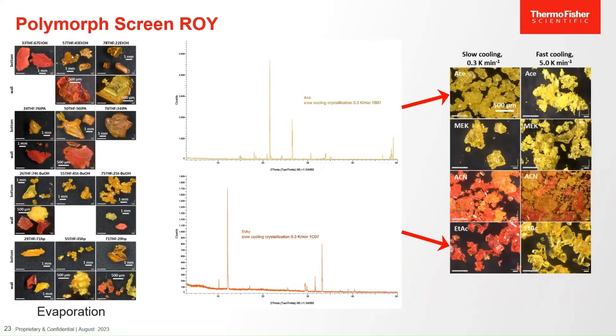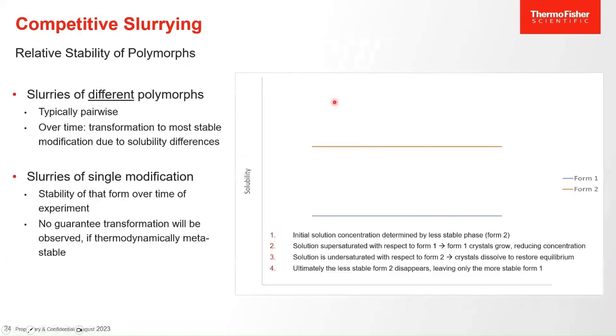So here you see an example of outcomes from a typical polymorph screen. This is a sample compound that we've used for demonstration processes. The compound is commonly known as ROY, red, orange, and yellow, and it's pretty obvious why it carries that name. Different polymorphs have different colors. They can be identified in some cases simply by looking at them. And you can see here microscope images from different crystallization conditions, different solvents, cooling crystallization, slow cooling, fast cooling, and different solvents. And these give you different outcomes. And characterization by X-ray diffraction shows you unambiguously that this yellow material here is not the same as this red material here. The relative stability is determined by competitive slurrying.